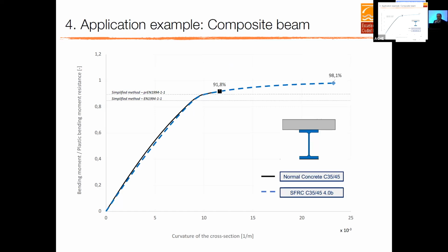So what is the impact of this in a structure? Here we selected an example. This example is a composite structure, where you see a steel profile and this concrete flange. In the x-axis we have the curvature of the cross section, and the bending moment in the y-axis. For the plain concrete in the compressive head of the composite beam, we are getting 91.8% of the plastic moment, and a rotation of approximately 12 m^-1.